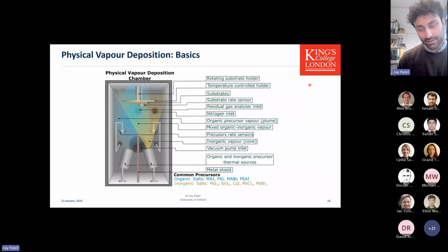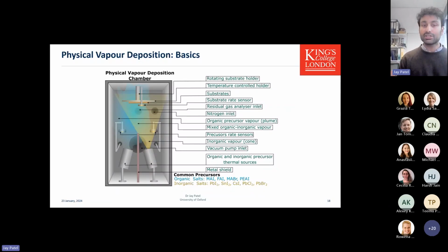So how does a physical vapor deposition system work? Well, in the case of perovskites, you have different sources in this chamber, and the chamber is pumped down to high vacuum. You have an organic source and an inorganic source, and essentially these materials are evaporated simultaneously, and you get a reaction on the surface, and you form this perovskite material.